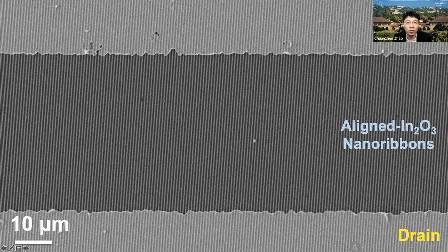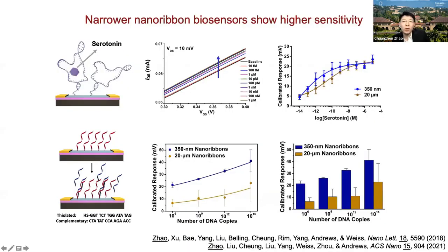Now, with this fabrication technique, we were able to make highly aligned and highly controllable nanowire transistors. Here we have the source and drain electrodes. In between them are those patterned indium oxide nanoribbons or nanowires. And between each pair of electrodes, there are around 1,850 wires. The number and the spacing can both be controlled precisely using different stamps. And the source-drain electrodes shown here were actually patterned by conventional photolithography. You can see those zigzags from the conventional photolithography compared with the precise control achieved by chemical lithography in the indium oxide nanoribbon area. We then compared the sensitivity of different widths of nanoribbons.